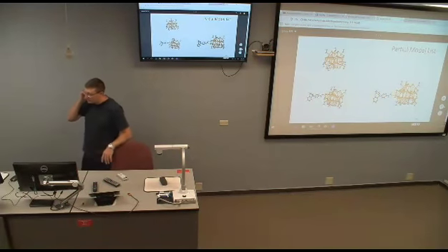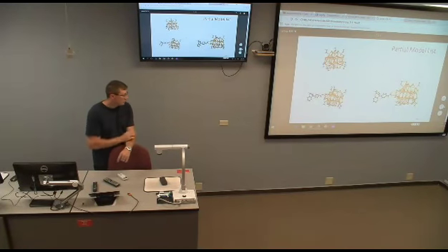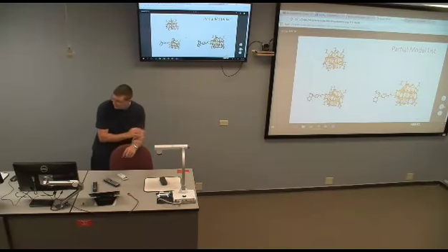Experimentally, people have been looking at these different types of groups for hole extraction, viewing whether the linker group bound to the organic pieces can dictate the speed or success of hole transfer from the quantum dot to their larger organic systems. And so